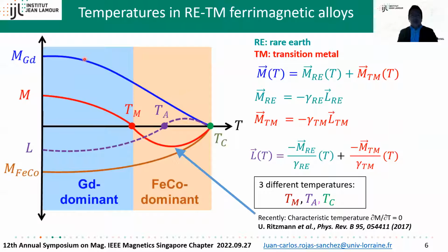This is an amorphous alloy made by sputtering, where we have two magnetic lattices, one given by the rare earth and the other by the transition metal. The total angular momentum is given by this relationship, where gamma is the gyromagnetic ratio. So we have several characteristic temperatures. In this case, gadolinium is the rare earth and iron cobalt the transition metal. When the total magnetic moment cancels out, we have the magnetic compensation temperature, and then here we have the angular compensation temperature. And then we have the Curie temperature, when the system is no longer ferromagnetic but paramagnetic.